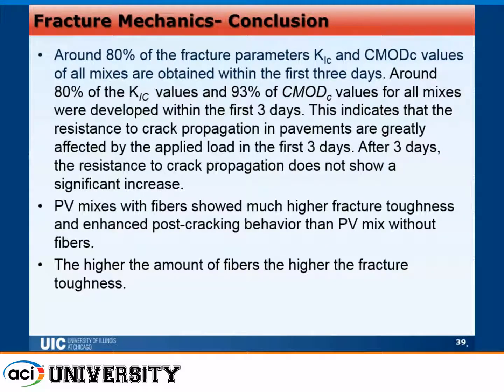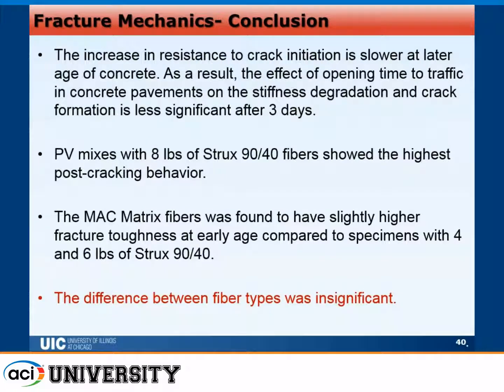As a general conclusion, because I'm running out of time, most of the results were obtained before or at 3 days of concrete age, especially for the critical crack mouth opening displacement and the stress intensity factor. And the difference was not really significant between the types of fibers.